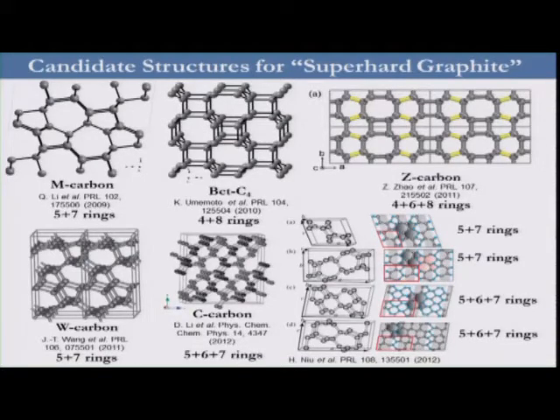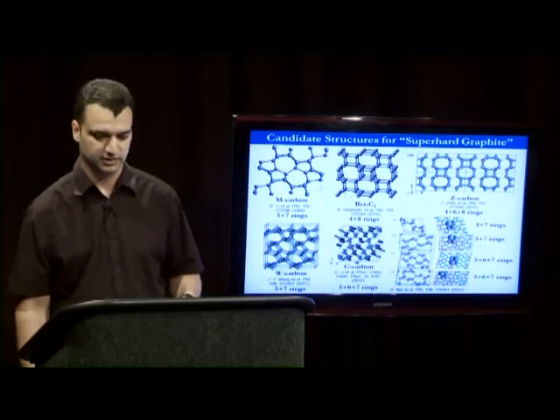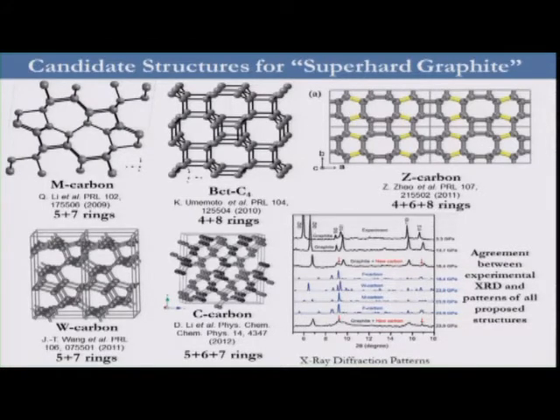We can use this concept and mix different rings, making pairs like even-even, even-odd, or even-odd-even. As you can see in the picture, this yields an infinite number of phases for super-hard graphite. And surprisingly, if you look at the diffraction pattern for all the proposed phases, they all match the experimental XRD data and can fairly explain it.